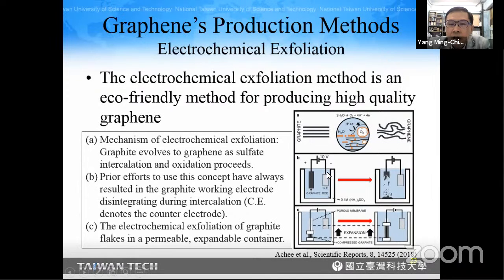Here we have a counter electrode connected to the graphite rod as the positive electrode. After a while, given a voltage of 10 volts of current, the graphite rod will disintegrate into flakes, and these are supposed to be graphene. But this makes the graphene difficult to collect.